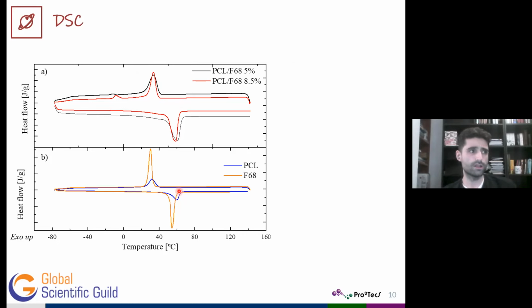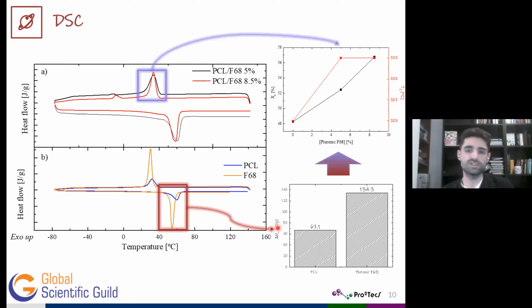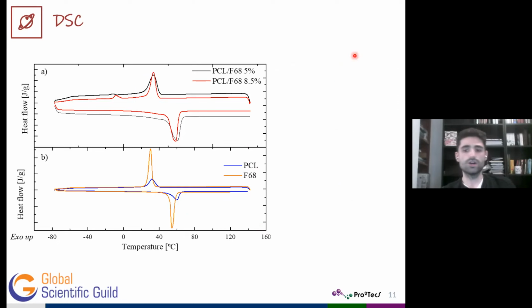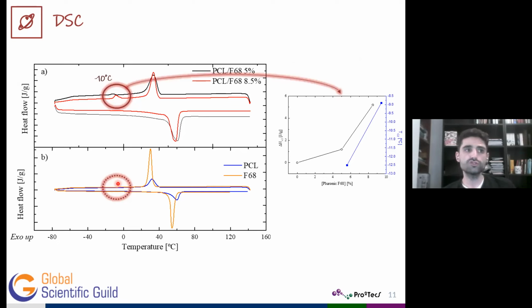As a consequence of that, the incorporation of Pluronic into neat PCL promoted the crystallization process, and that was noticeable not only in the higher crystallinity degree corresponding to the black line in the graph on the right, but also in the higher crystallization temperature corresponding to the red line. On the other hand, these polymer blends exhibited a second crystallization step at around -10°C, and although that peak didn't appear in the pure compounds, its energy release rose with the addition of Pluronic, highlighting not only its reliance on the presence of Pluronic, but also on its content.